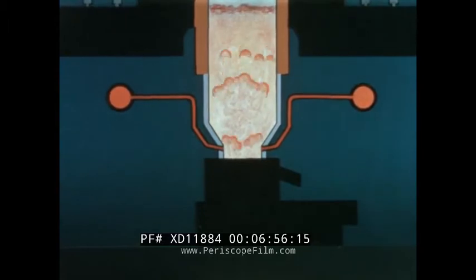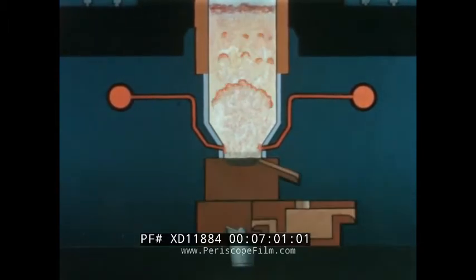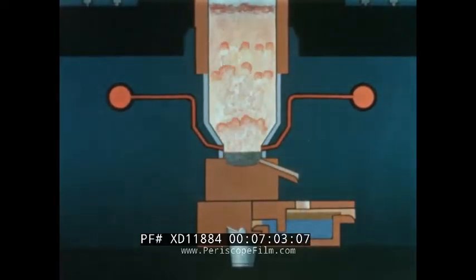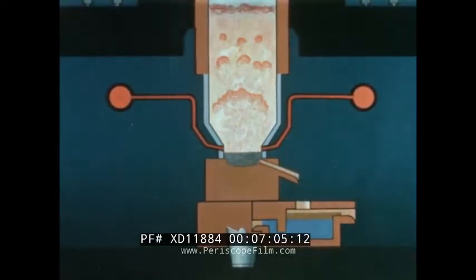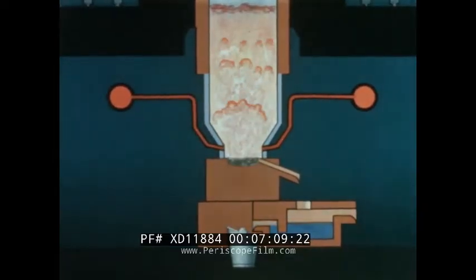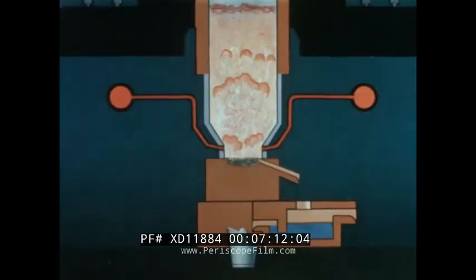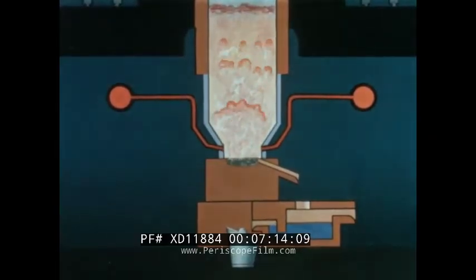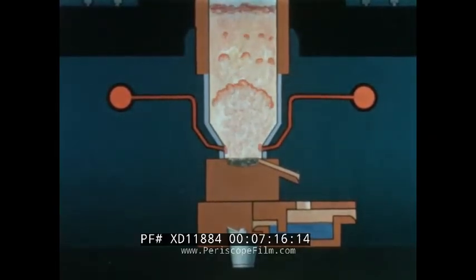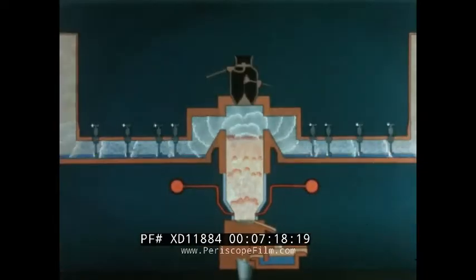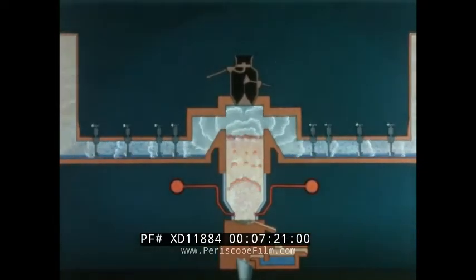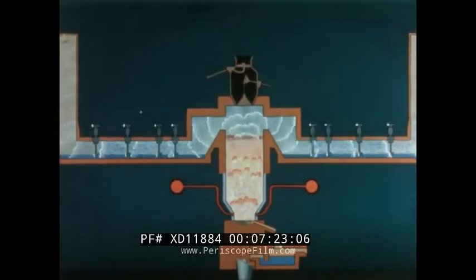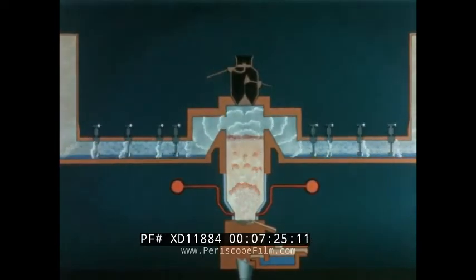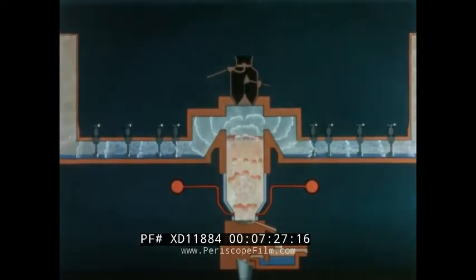The lead collects in the bottom of the furnace and in so doing recovers copper and precious metals present in the charge at a high efficiency. The remainder of the furnace charge, that is gangue, coke ash and fluxes, forms a molten slag. Lead and slag are then tapped into the forehearth to be separated. The mixture of furnace gases and zinc vapor, which rises to the top of the furnace shaft, has a temperature of about 1,000 degrees centigrade and contains approximately 5 to 7% of zinc by volume.